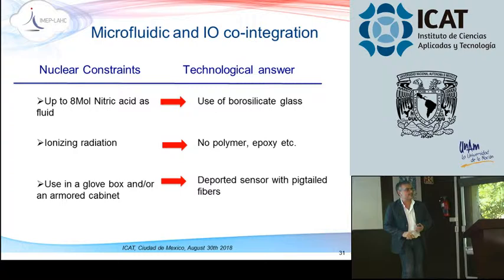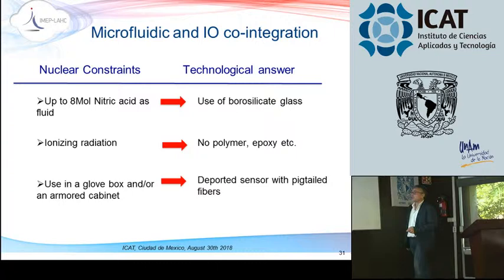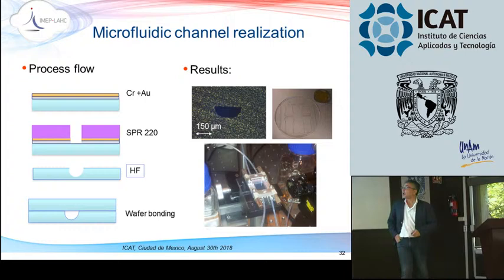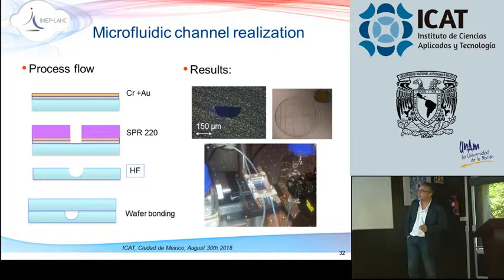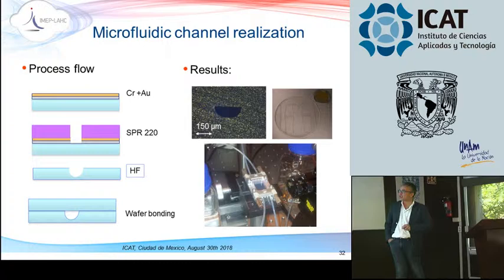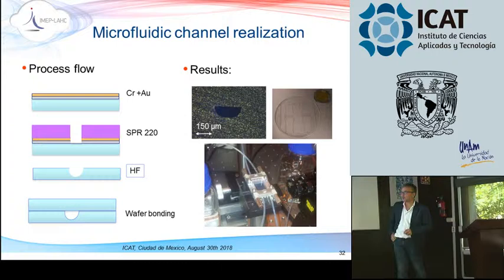And, of course, we have to use it in a glove box or in an armored cabinet, because we are not allowed to kill students or technicians. I don't know how it is in Mexico, but in France we are not allowed to do that. So we need a deported sensor with pigtail fibers. So we developed a technology for realizing microfluidic channels without any glue. We did a process flow, etching some grooves inside the glass, and then we did some molecular wafer bonding. Molecular wafer bonding is based on van der Waals force adherence, and then you make some annealing and treatment to create covalent bonds between the two wafers.